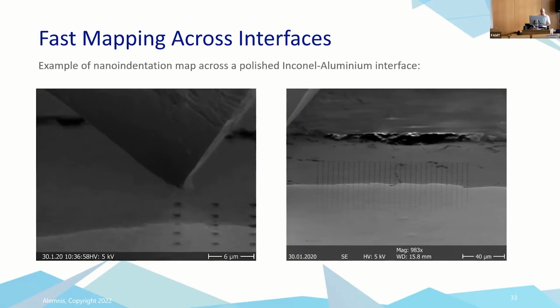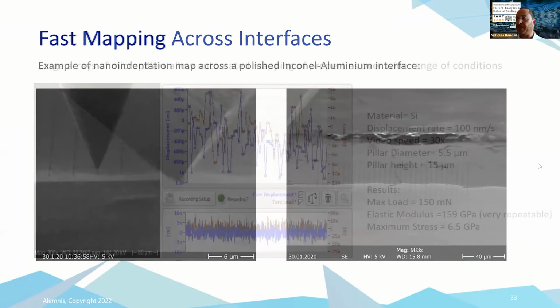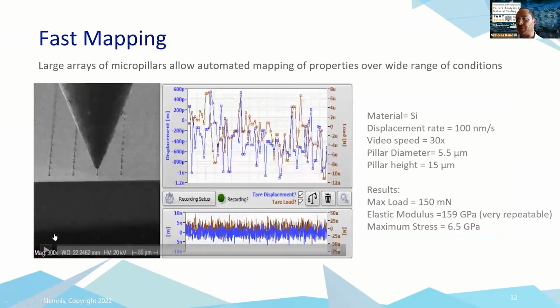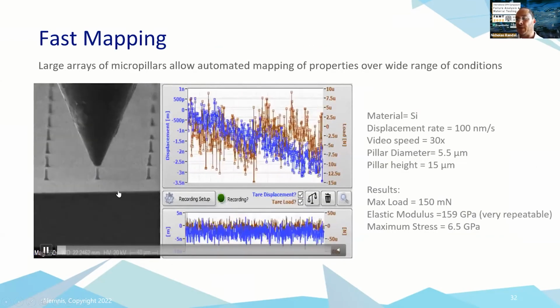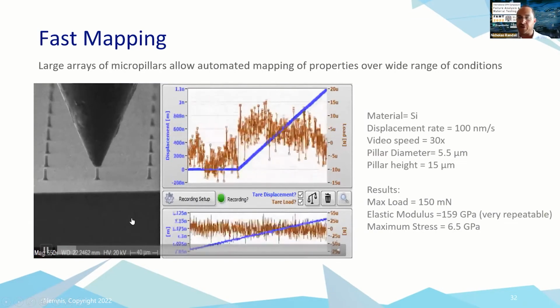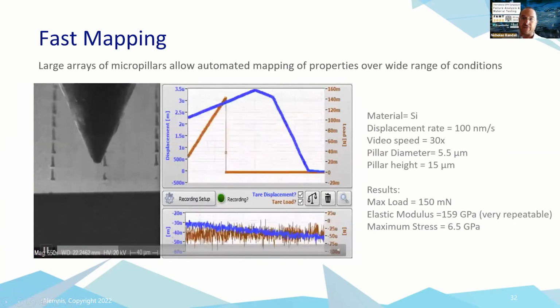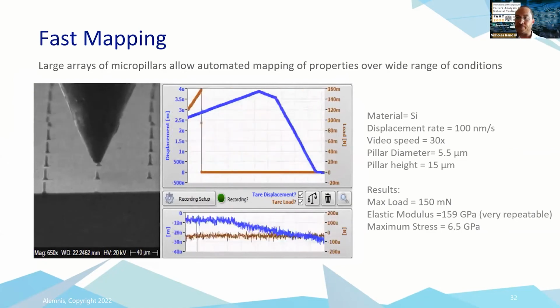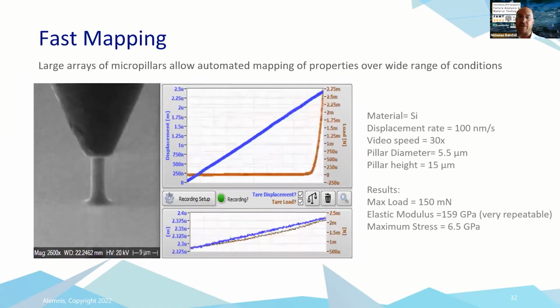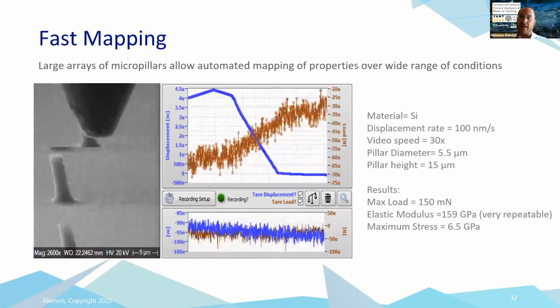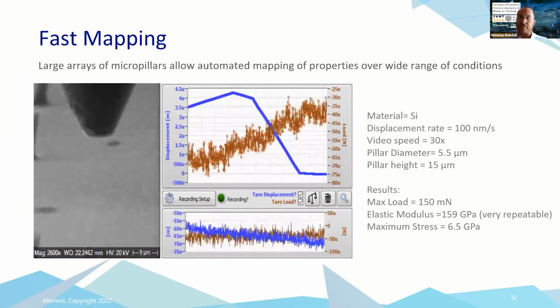And for some of the other push tests, the cycling test, you're not using the pyramidal face, you're using a different type of... Yeah, so for pillar compression, we'd be using a flat punch. The whole point of the flat punch is that on the end of this is a flat punch, so that we don't have to worry about the contact area changing. It's always the same. We basically have a flat on flat contact, and so we have a fixed contact area. And so we can take that error out of the equation for stress strain.